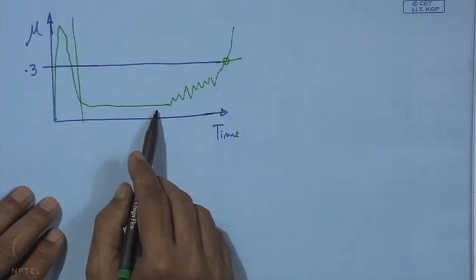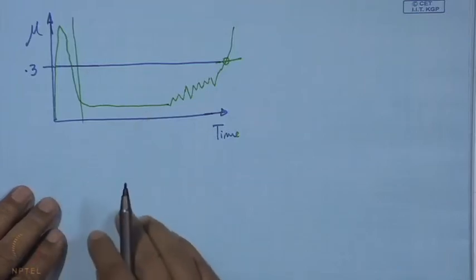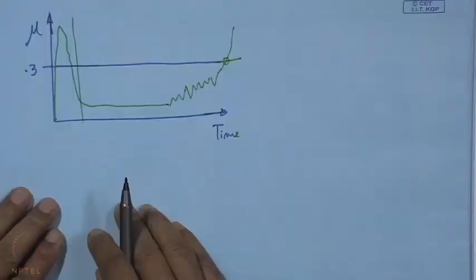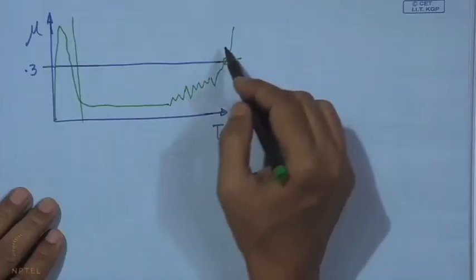Now, to get a very good value, obviously, at the very beginning, as we have said, the roughness of the substrate surface, its high points or surface asperities, apart from the chemical inertness or very low chemisorption, those conditions are there. The hardness of the substrate should also be properly monitored and taken care of, and then only a tribological coating at the top of that can work. But this map clearly shows how good or how poor the coating is and how long it can survive.